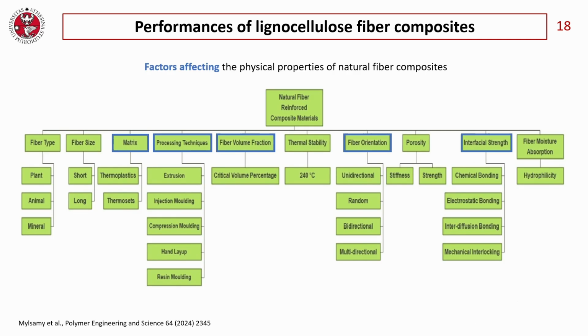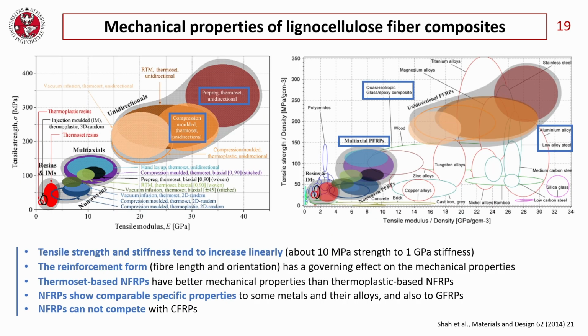Last slides, we have many factors that affect the physical properties of this material, in particular the kind of matrix we select, the processing techniques, the fiber content, the fiber orientation, and the interfacial strength. It is difficult to have a general overview about the mechanical properties of this material, but you can see that in terms of strength and stiffness, all the natural fiber composites follow a linear trend. In particular, we have an increase of 10 megapascal of tensile strength if we increase the stiffness by 1 gigapascal.